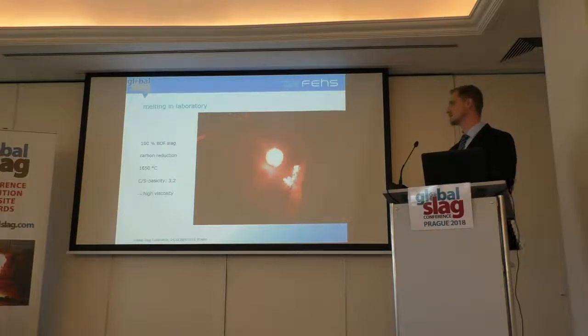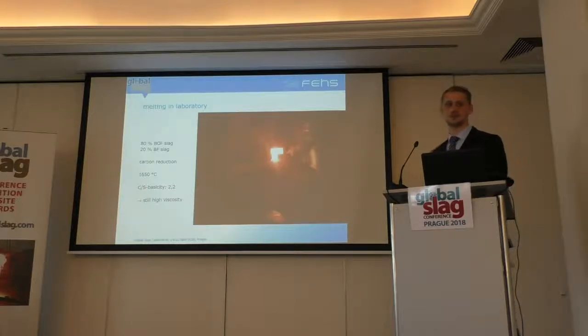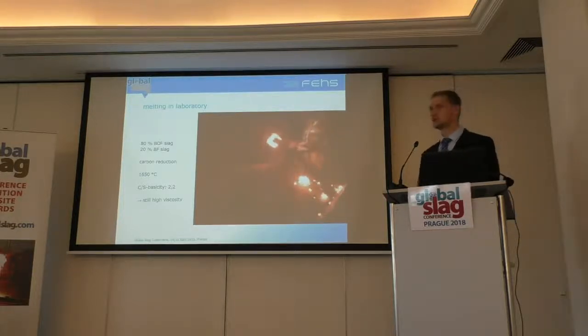So we tried to decrease the basicity and so decrease the viscosity by adding some blast furnace slag, 20% of blast furnace slag. There we are able to reduce the CaO/SiO2 basicity to 2.2, but as you can see here, it's more or less the same problem. The reducing of the basicity from 3.2 to 2.2 doesn't really help.